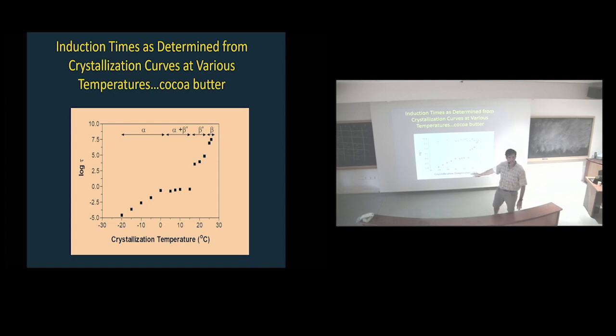Absolutely. That is very sensitive to, I mean, you would have a much lower free energy of nucleation for an alpha form if you did that plot. Oh, it's just structural. Because what happens is the viscosity of the melt increases to such a point that the molecules cannot diffuse anymore. And there seems to be a time constant related to the alignment of these long chains. There's 3 of them, there's a glycerol core. It seems to be computationally difficult. So there's a definite time constant; it's almost like the supersaturation is calling you to crystallize, but this rearrangement that needs to take place in order to form the crystal is very expensive in terms of time. That would be reflected in the induction time. Yeah. Absolutely. That's part of the thing that is missing in there because the diffusion gets screwed up for everybody.